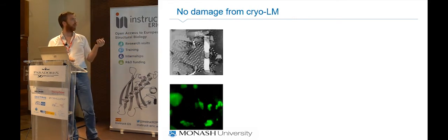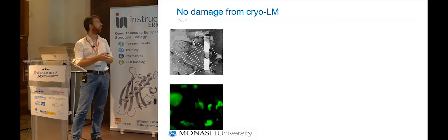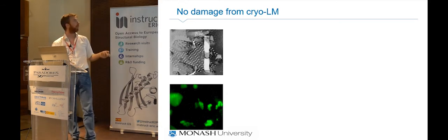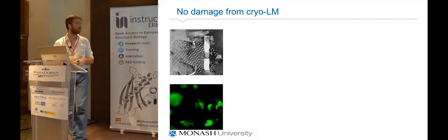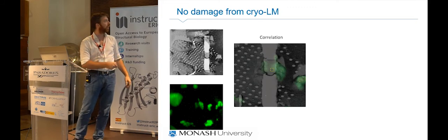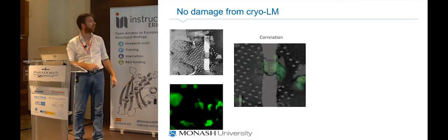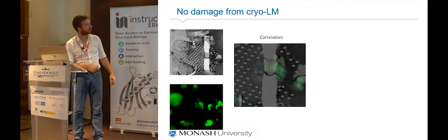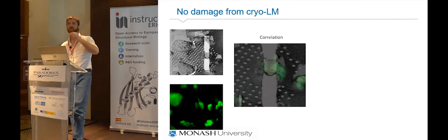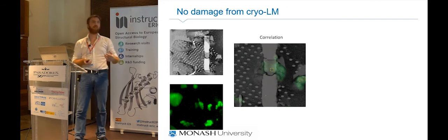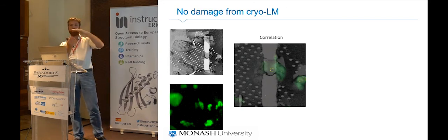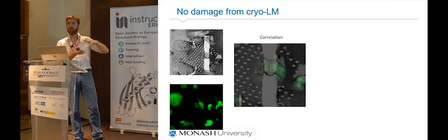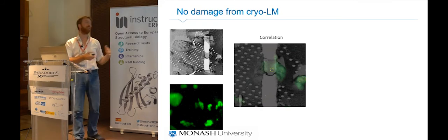Then one thing that we were asked for when we submitted the paper was, can you actually see fluorescence out of the lamella, which is 200 nanometers? And the answer is yes. So this is a lamella, which has the proper thickness for TEM, and this is the fluorescence. It is limited, it's only 200 nanometers. Everything else is emitting from the whole cell, and the optical plane, because it's a wide field microscope, is about 1.5 microns in this case.